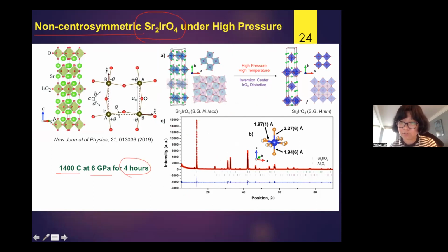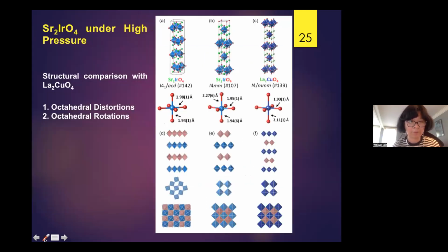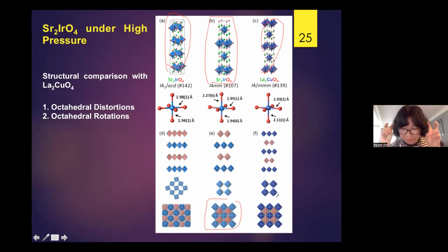You can see there is no octahedral rotation, but we have oxygen splitting in the system, which, as I will explain later, we don't like very much. So this is the new phase we got. Here we make the comparison: this is the ambient pressure reported phase, this is the high-TC superconductor, and this is what we made under high pressure and high temperature. We can clearly see that the rotation is now fixed, like in the high-TC superconductor, but there are still some problems. We have the oxygen splitting, so it's not fully occupied, whereas for the high-TC it's fully occupied.